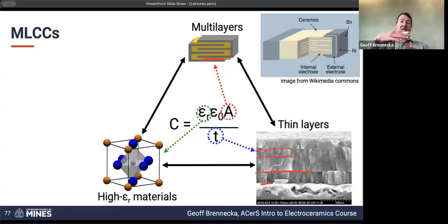So the roughness of that surface between the electrode and the dielectric layer absolutely is an important parameter. The higher the roughness, the higher the surface area. The higher the area, the higher the capacitance, right? So on one level, you could think of that as being a good thing because it gives you more area. But because of the field enhancements that go along with those sharp points or just any curvature at all, that is going to limit the amount of voltage that you can apply before you get breakdown, before you get other sorts of field concentrations and additional leakage and that kind of stuff.